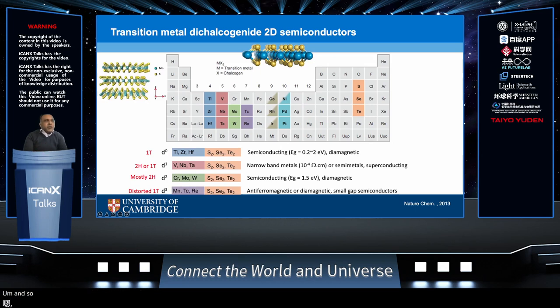And so we can isolate these individual sheets. They can be in the semiconducting form, so their electronic properties are characterized by their actual atomic structure. In the case of molybdenum disulfide, the 2H phase or the 1H phase for a monolayer is the semiconducting form. So we can make good transistors and electronic devices out of this 2H form. The unit cell is trigonal prismatic.